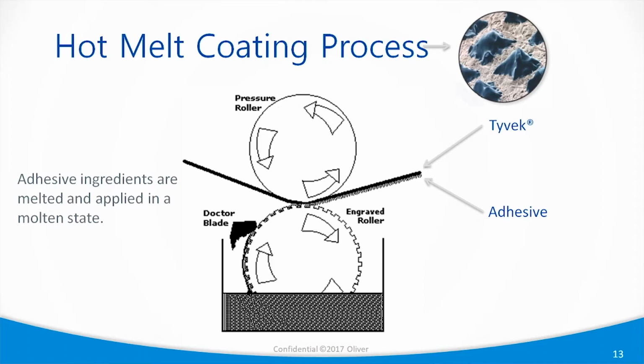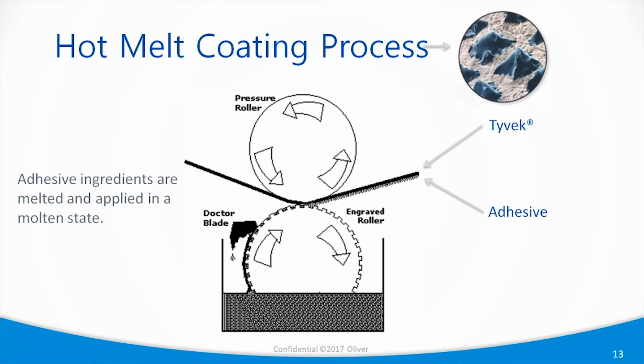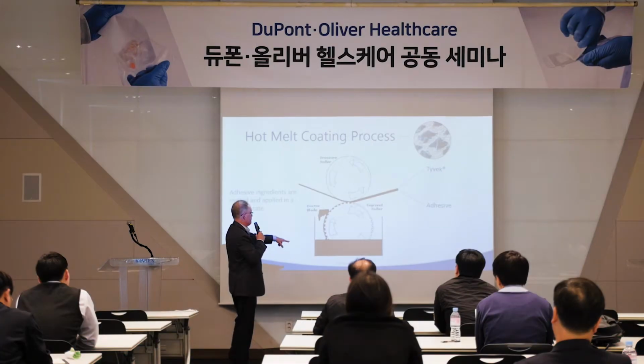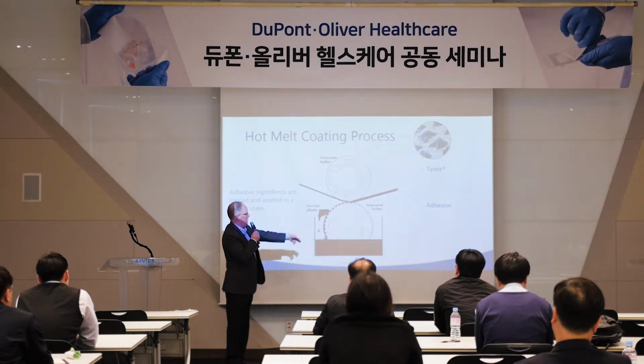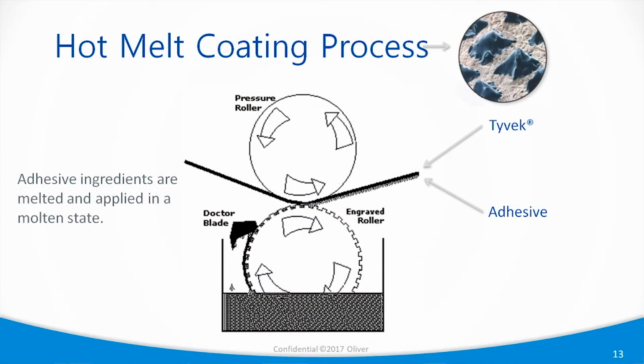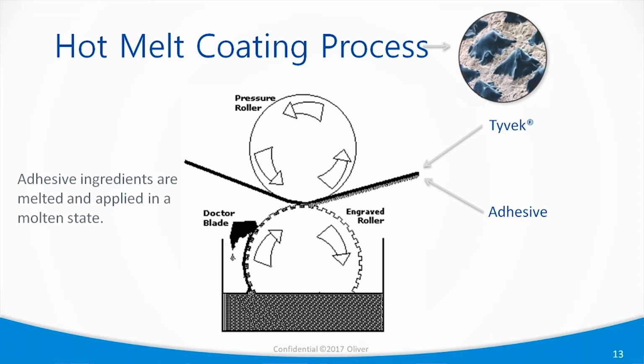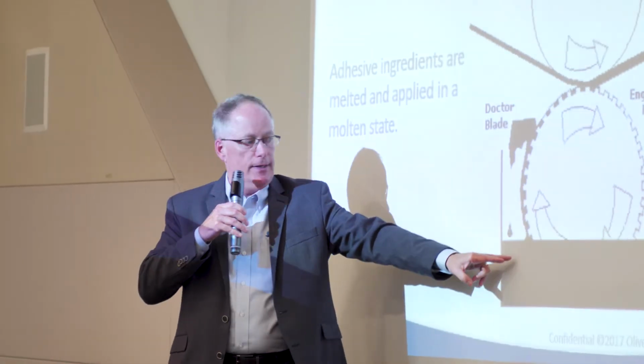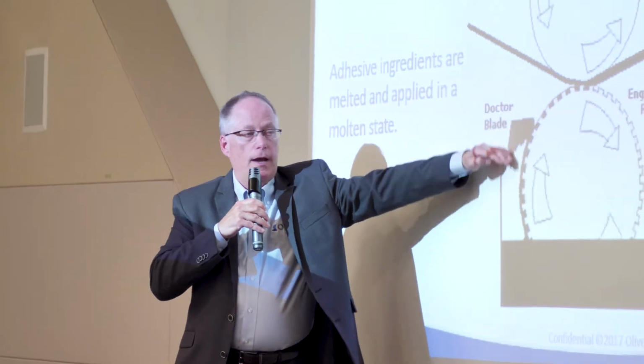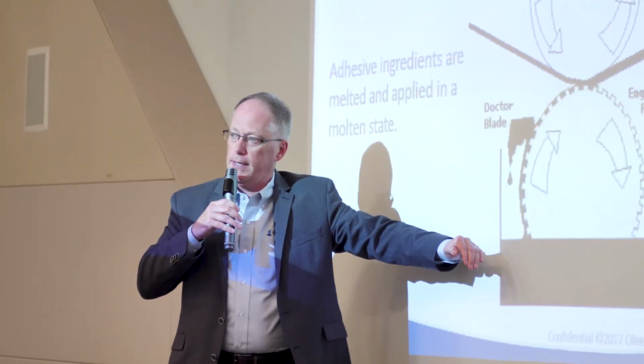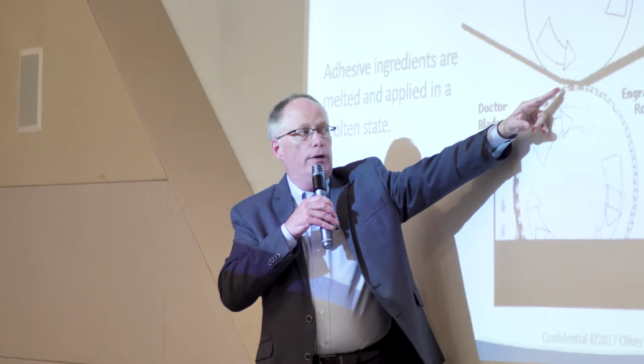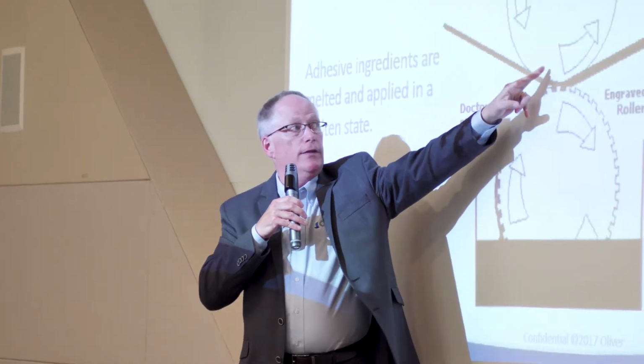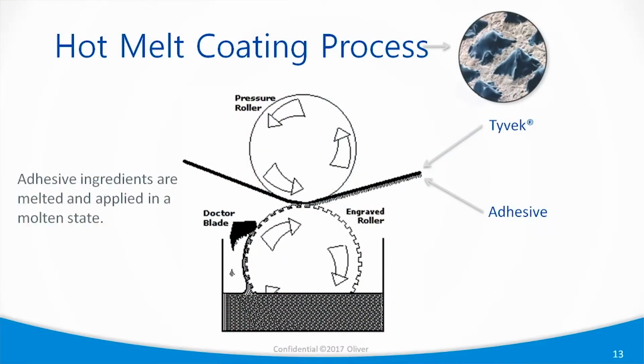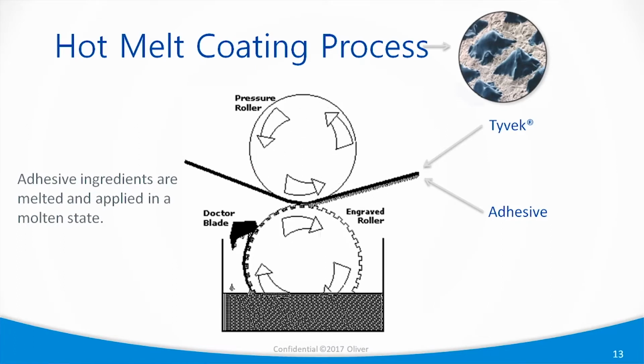We're melting those components down, pumping them through a series of pipes and into a bath where we have a cylinder. Very similar to gravure printing, it's got little micro pockets etched into it that pick up the adhesive, and then a doctor blade removes the excess adhesive. Those micro dots are applied to the Tyvek right at this interface. And again, we're talking about those micro dots of adhesive.